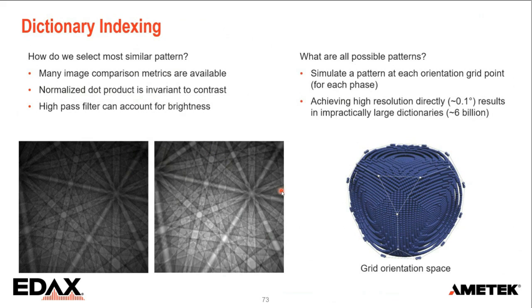But when you do that, we need to have a simulation. And for that, we need to identify what all the possible patterns are. We can just say, okay, we need to simulate a pattern for all possible orientations, for all phases. And you need to do that at a given interval. But you have to be a bit careful, because if you want to do dictionary indexing this way, where you just look at 0.1 degree orientation changes, then for cubic, you're already talking about billions of simulated patterns that you have to compare every single pattern against.